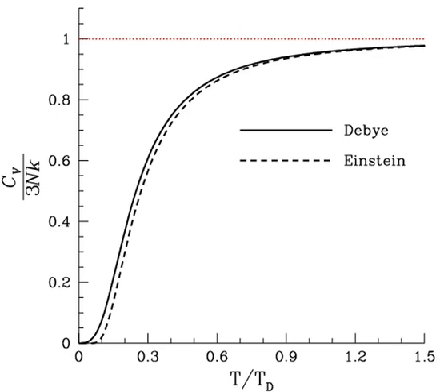Solid phase. For matter in a crystalline solid phase, the Dulong-Petit law, which was discovered empirically, states that the molar heat capacity assumes the value 3R. Indeed, for solid metallic chemical elements at room temperature, molar heat capacities range from about 2.8 R to 3.4 R. Large exceptions at the lower end involve solids composed of relatively low mass, tightly bonded atoms, such as beryllium at 2.0 R, and diamond at only 0.735 R.